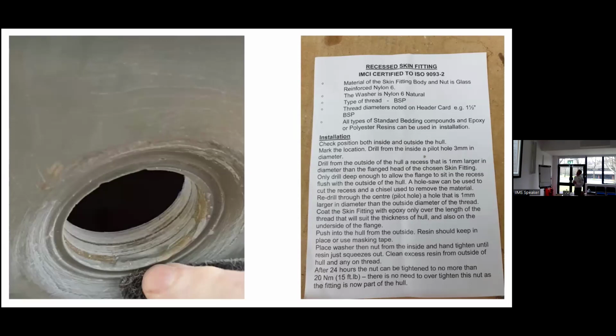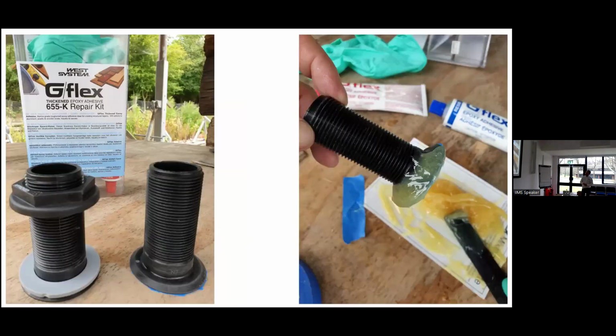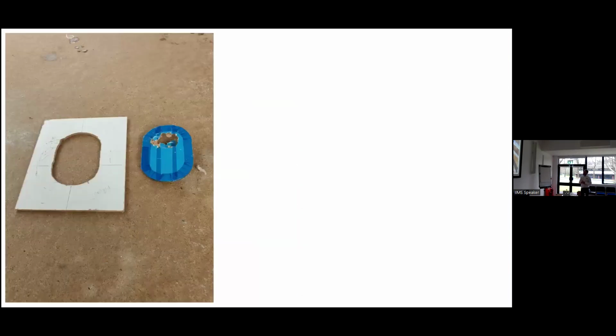In the instructions, it suggests using either Sikaflex or epoxy to bond these fittings in. Well, again, I used G-Flex to do this. And now the manufacturers have actually written G-Flex in as a means to do this, because you buy it in small quantities and execute a really good bond. In the next slide, you can see it's quite messy, sticky. I should have worn gloves for that picture. Then I just set them in loosely, and the next slide I think shows that, and I then tightened them up by hand and then tightened them up once the epoxy cured.